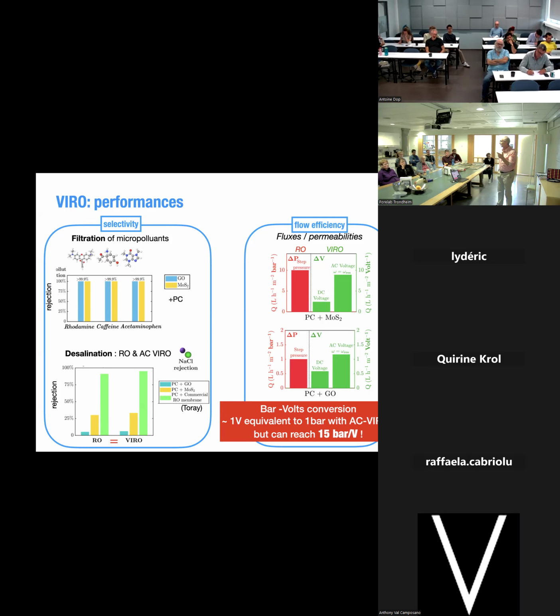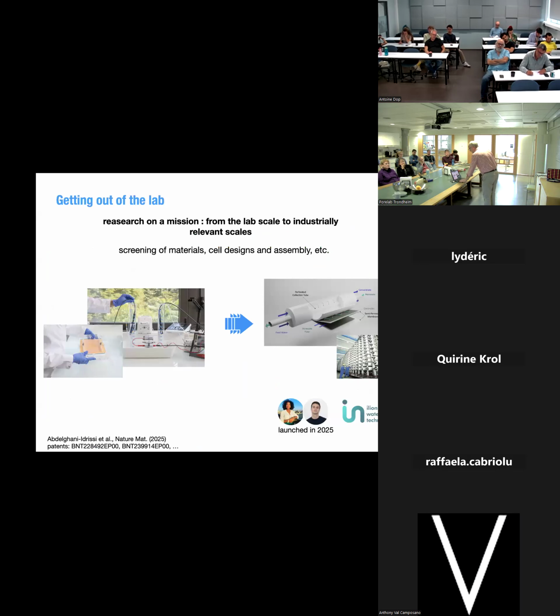It happens that for these experiments, typically 1 volt is equivalent to 1 bar. But by playing with the geometry, if you reduce the size of the polycarbonate membrane, you boost this performance completely. We went up to 1 volt equal to 15 bars. So you could do nearly desalination at 2 volts, which starts to be very nice because 2 volts is a photovoltaic cell. So that's what we started to play with.